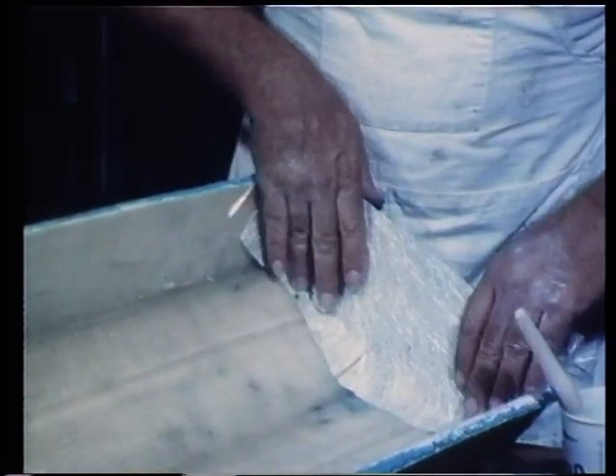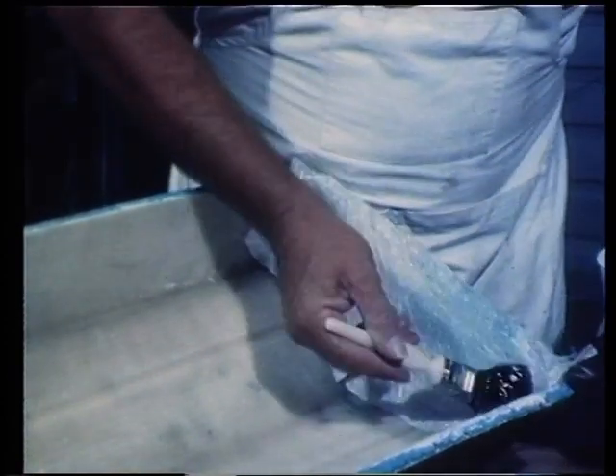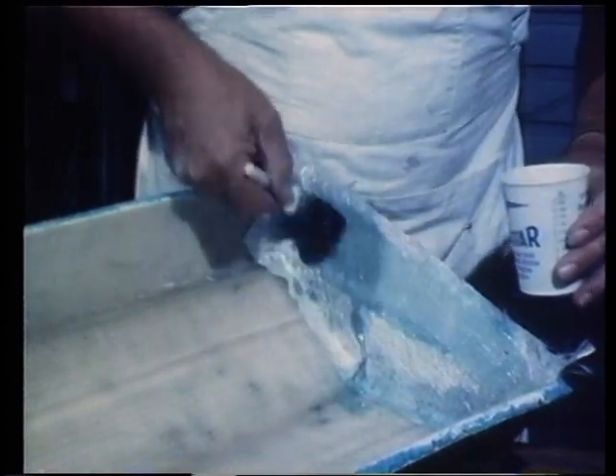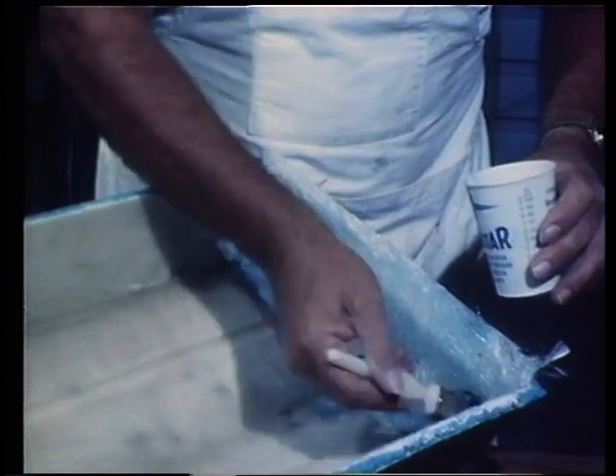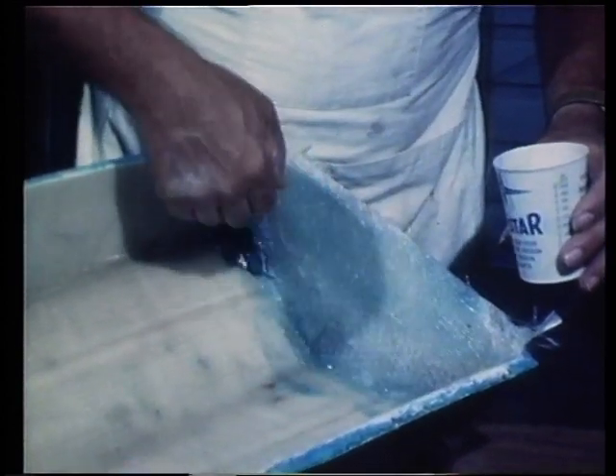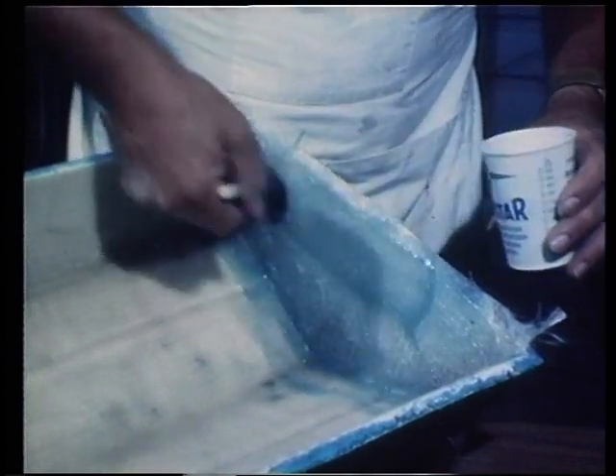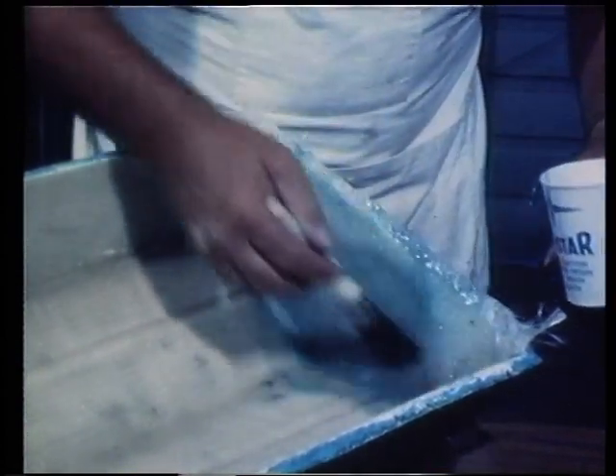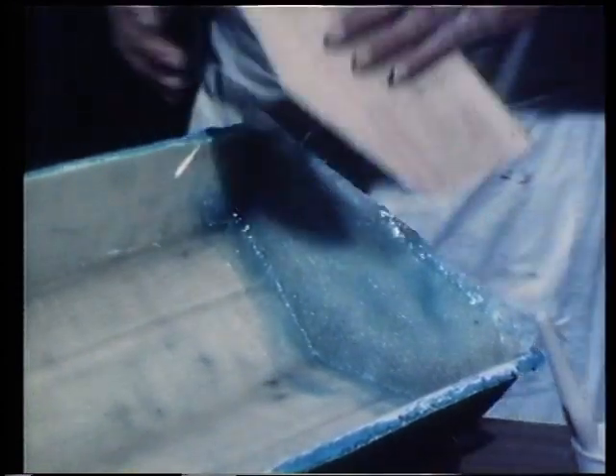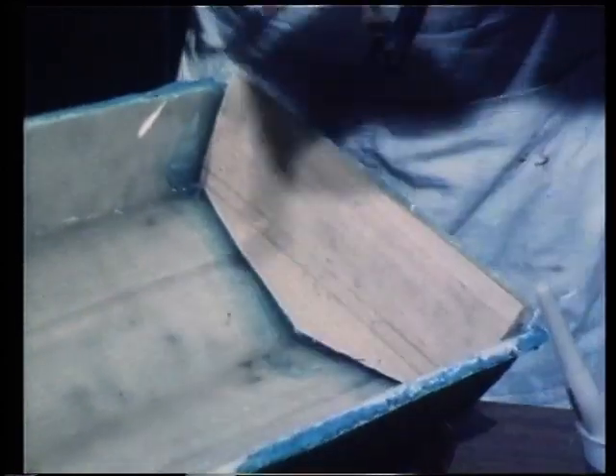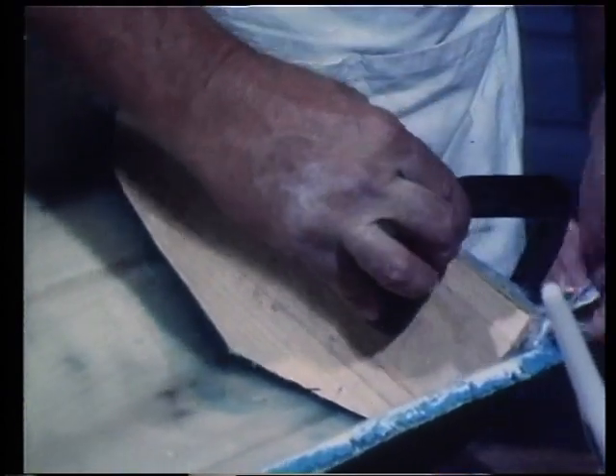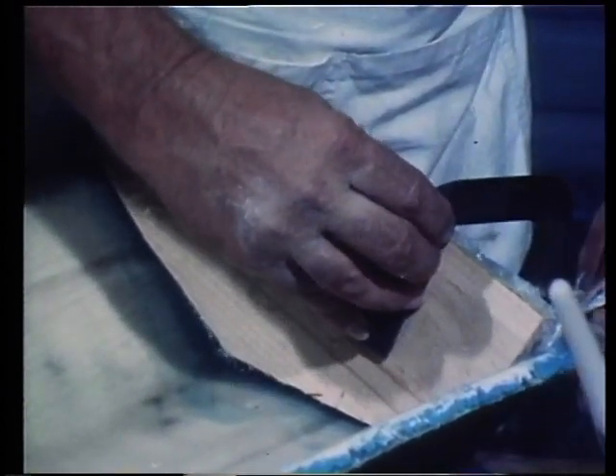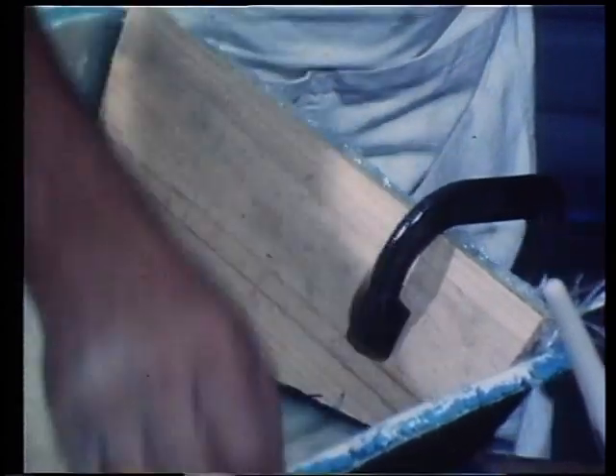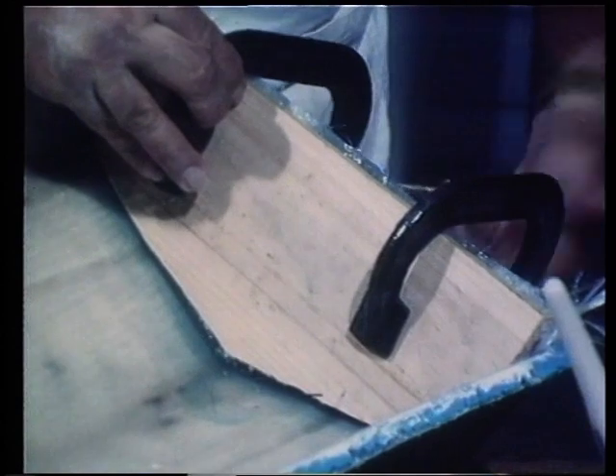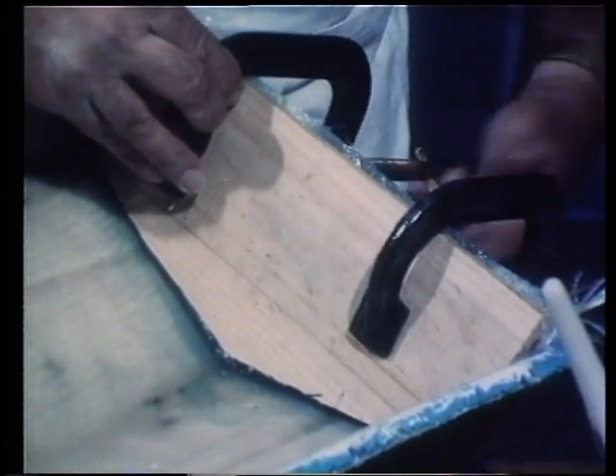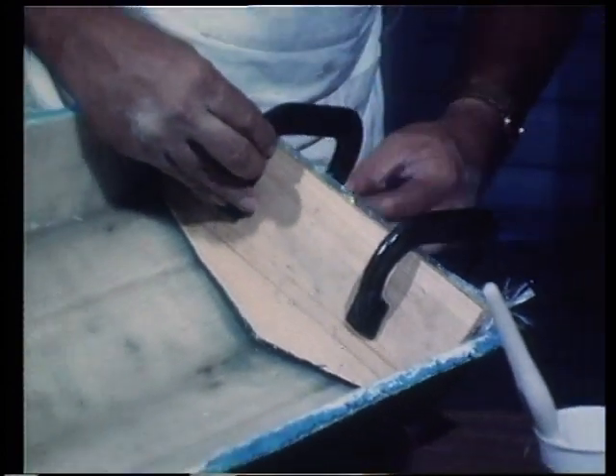glass and the resin. We want a good, solid, thick, sloppy, if you like, layer of glass and resin in there, so that when we clamp the timber in, it really squeezes down in, and the resin actually squeezes into the grain of the timber and adheres it well and truly to the laminate underneath. So we just brush plenty of resin in there, apply the sawn plywood transom, and apply pressure using these G-clamps. Now, this is exactly the technique used for a larger boat. It doesn't vary in any way, except of course for the size of the clamps, for the size of the boat. So that's really pulled the timber down into the laminate that I've just applied.